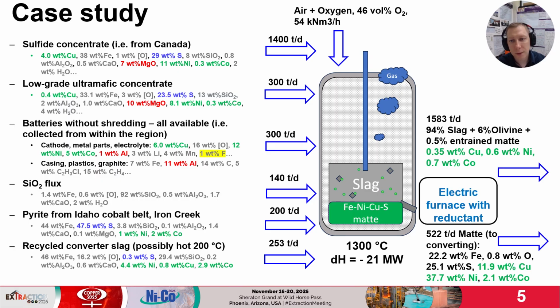The furnace produces slag and matte mixed together, so a separate vessel is required for better recovery. The best one is electric furnace. Still, the slag contains suspension of olivine crystals, which have lower density and should float on the top, and about 0.5% suspended matte particles, which can be hard to settle. With these assumptions, the recovery into matte is calculated to be 91.5% copper, 95.2% nickel, and 49% for cobalt.